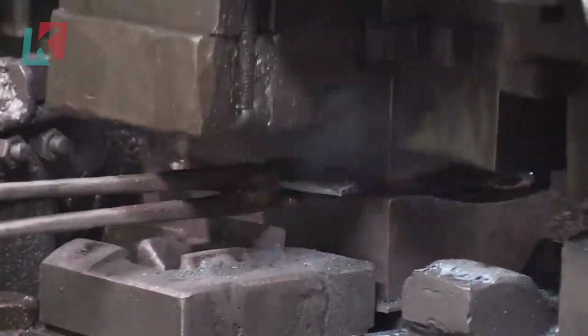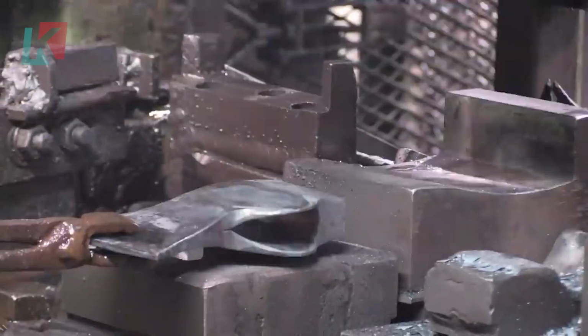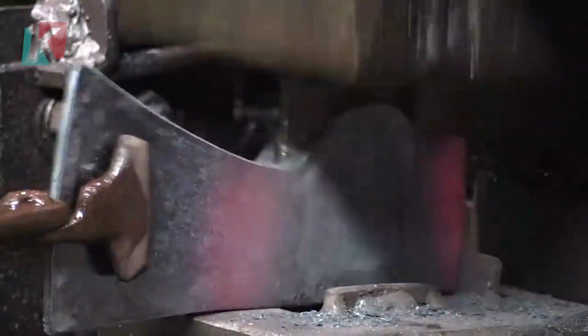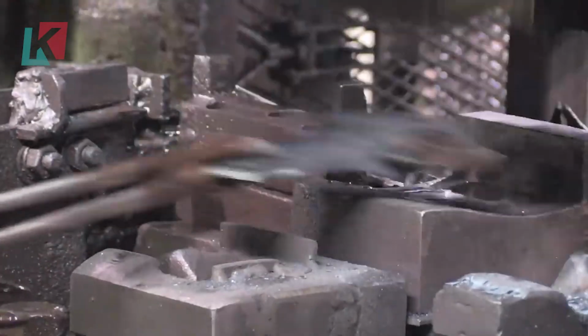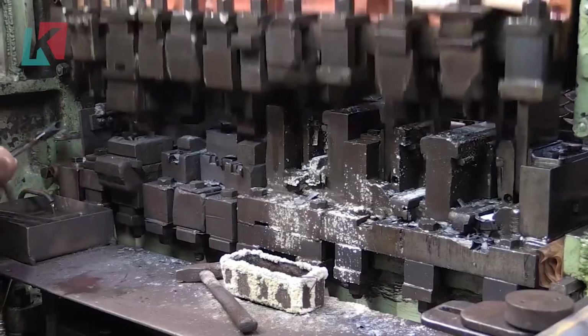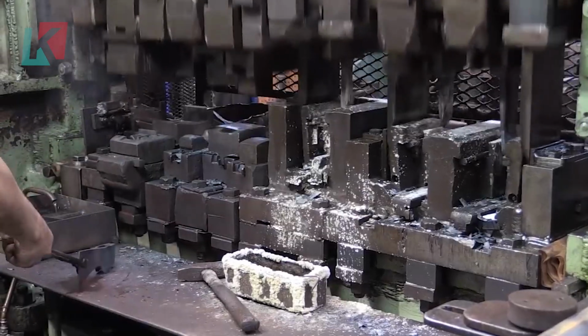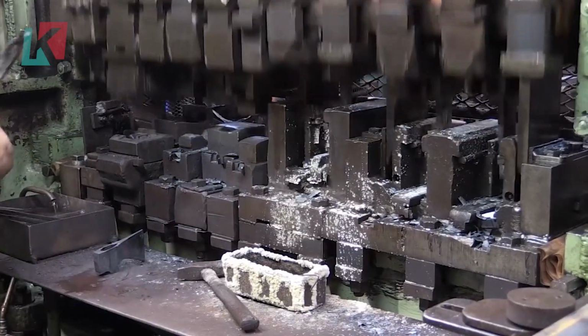Heat treatment is the final critical step. The cutting edge is heated to 1500 degrees Fahrenheit and quenched in oil, then tempered back to achieve the perfect hardness of about 57 HRC. Too hard and it's brittle, too soft and it won't hold an edge.